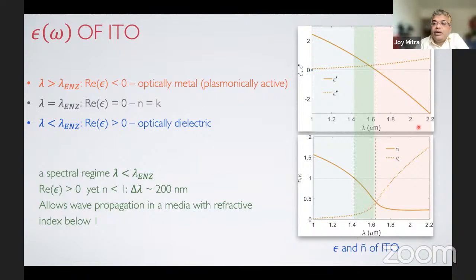As I said before, we entered these systems to explore the plasmonically active domain, which is the metallic domain. But now we are slowly transitioning into this narrow region, which is of the order of 200 nanometers in width, and which lies just below the lambda ENZ. So this unique combination of the refractive index being positive, the permittivity being positive and the refractive index being less than 1 in that wavelength regime allows propagation in a media with refractive index below 1. And let's see what happens then.